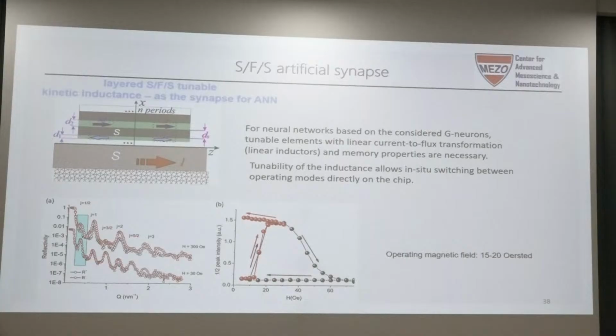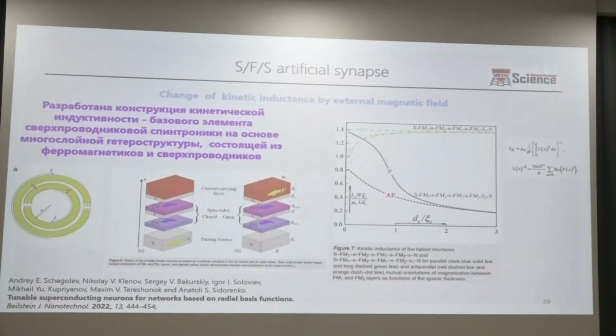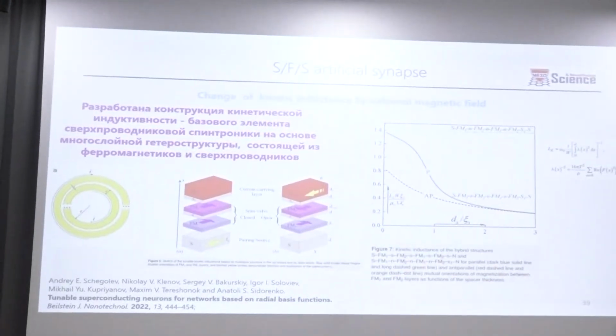Another base element, the synapse, can be constructed from an artificial magnetic material, a layered structure, which is illustrated here. A superconductor has one important parameter, so-called kinetic inductance. Each conductor has inductance, but if we have a superconductor where there are Cooper pairs, the kinetic energy of the movement of Cooper pairs gives an additional term to the inductance, the kinetic inductance. Kinetic because of the motion of Cooper pairs. Above the critical temperature, the kinetic inductance is zero. Below the critical temperature, it appears, and in this element we can change the kinetic inductance of the structure by changing the magnetization of the ferromagnet layer.